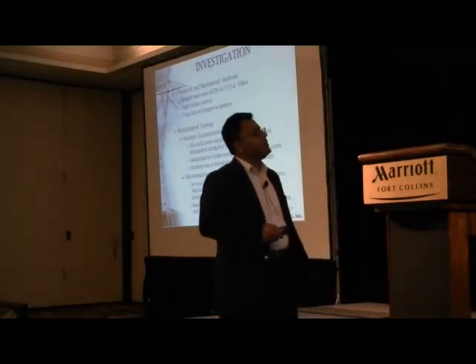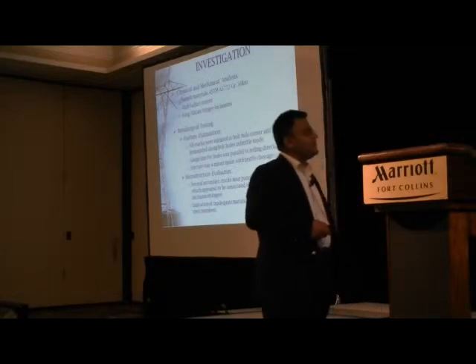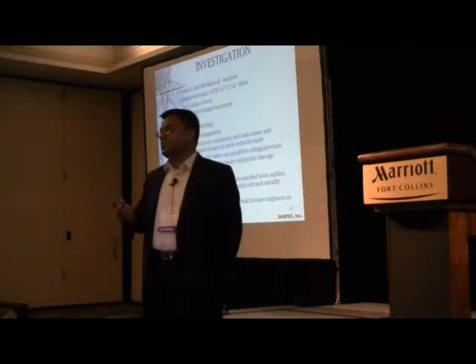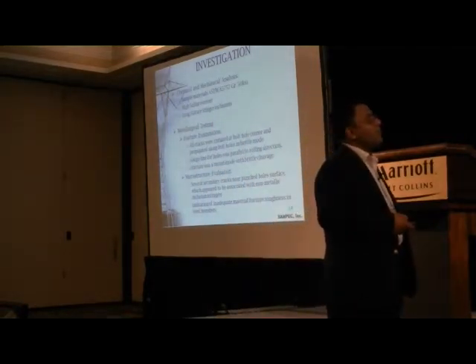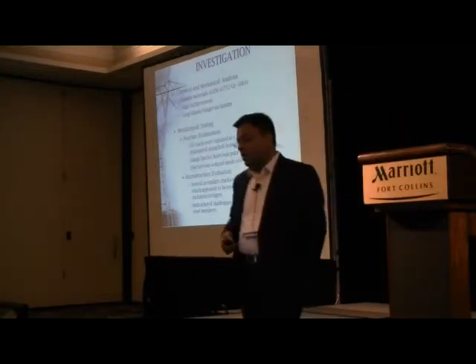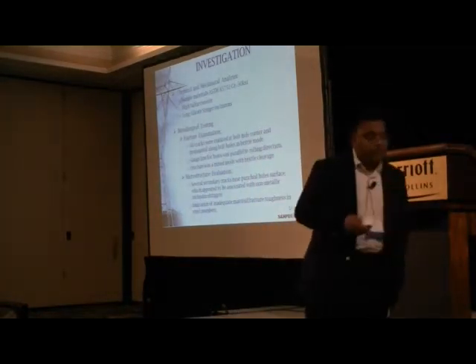The fracture was a mixed mode with brittle cleavage. Again, the lack of toughness. And when we did the microstructure evaluation, we found several secondary cracks because of the punch. If you punch a thicker material, you will have a lot of localized stress there. So we found secondary cracks near the punched holes that appeared to be associated with non-metallic inclusion stringers. Again, we have to be very careful what thickness we punch. And then, of course, it shows the indication of low material fracture toughness in the steel members.